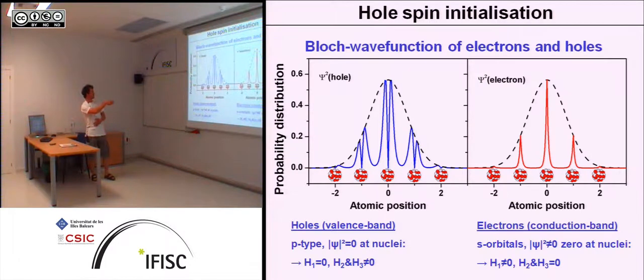Now here we have a hole, and because a hole is a valence band particle, the valence band in gallium arsenide or in indium arsenide consists of p orbitals. So you have this p symmetry, where the probability density goes to zero at the position of each nucleus of the host material. However, if you look at the electrons, they have s symmetry because they're conduction band. And that means the maximum probability is exactly at the position of the nuclei. And this now has a big influence on the nuclear spin coupling.